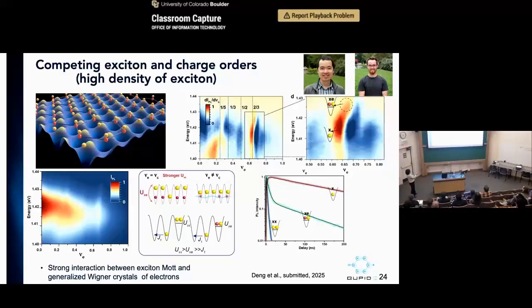And the charge and the exciton, if they have strong interaction, and in this case they do, then your exciton would also have to be pushed up to occupying higher energy states. In this case, we're going to look at an exciton lattice that is elevated by the charge orders. We hypothesize that when they occupy this high energy state, they would have a larger J because the potential is smaller. There's also some theory that has calculated that you can get to a larger J when the excitons are occupying the high energy band. So this is what we're trying to do.